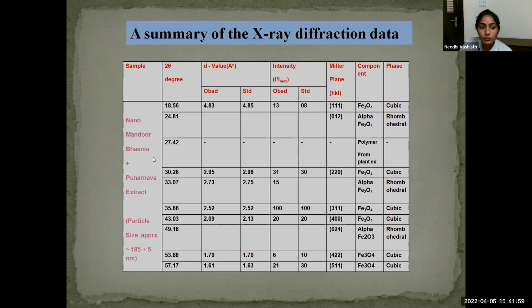The sample of nano Mandur Bhasma Punarnava extract particle size is approximately 185 plus or minus 5 nanometers. So we consider the 2 theta values and the value of d, where d is the spacing between the planes. Here is the intensity. From the above graph, we consider all this table: Miller plane components and the phase. As we see, Fe3O4 is a cubic form, alpha Fe2O3 is a rhombohedral form, and there are some remaining polymers from the plant extract in Mandur Bhasma, which remain in that form.